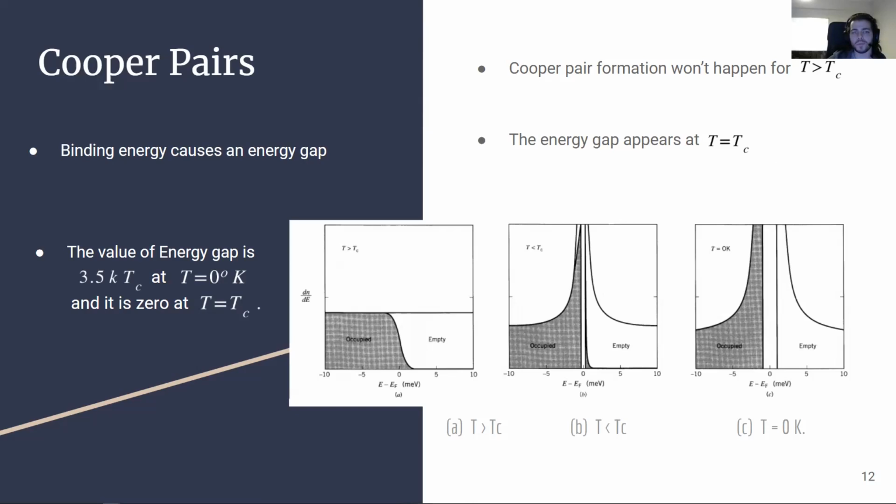So here, maybe we could also mention that since this theory is depending on the vibrations of the lattice, this could also give an explanation for why good conductors like copper and gold don't become superconducting. So when we are looking at bad conductors, worse than gold and copper, we see that they become superconducting.